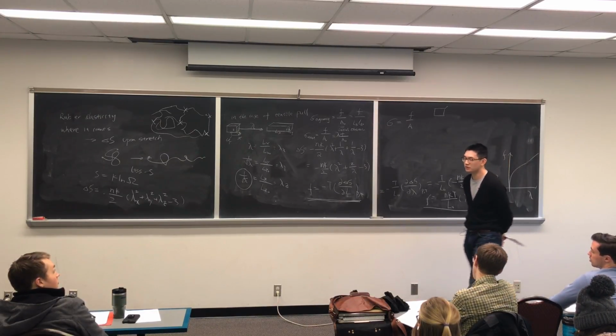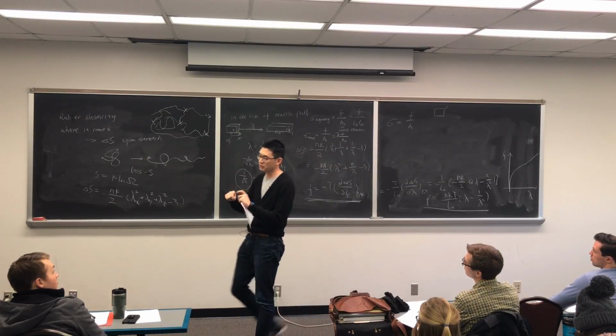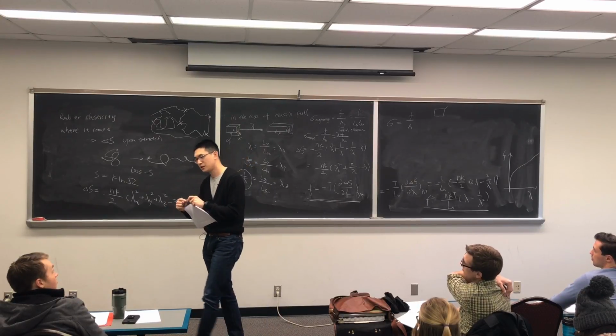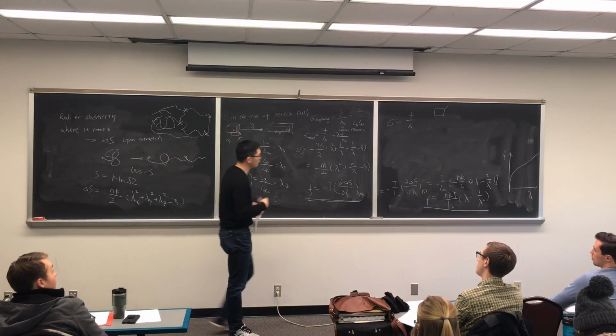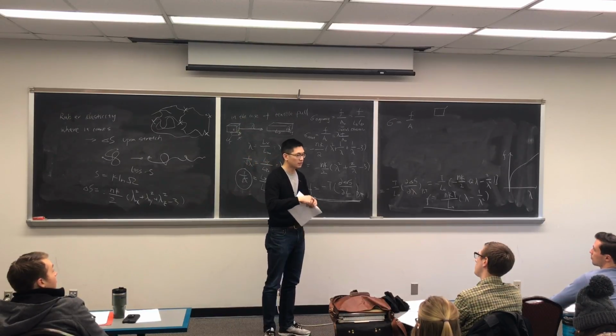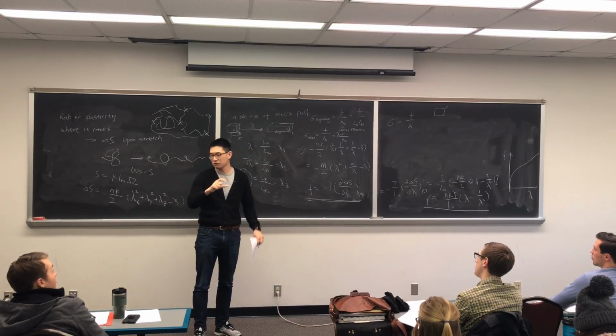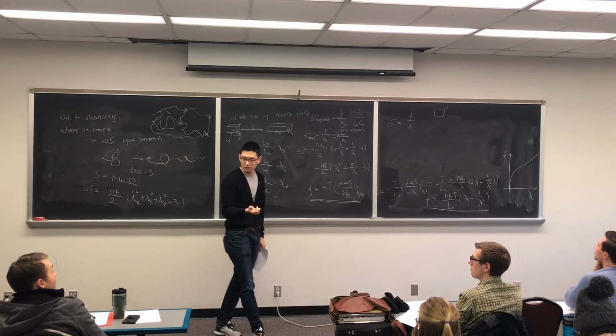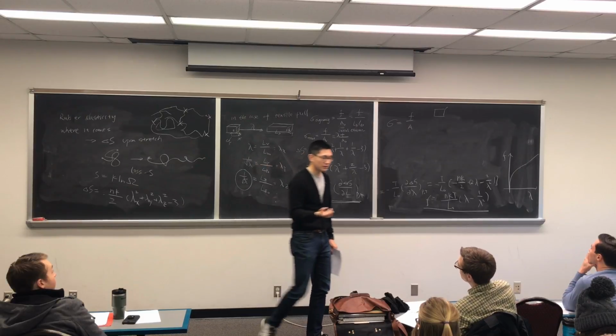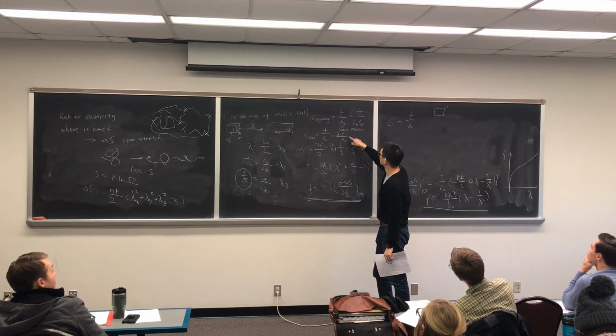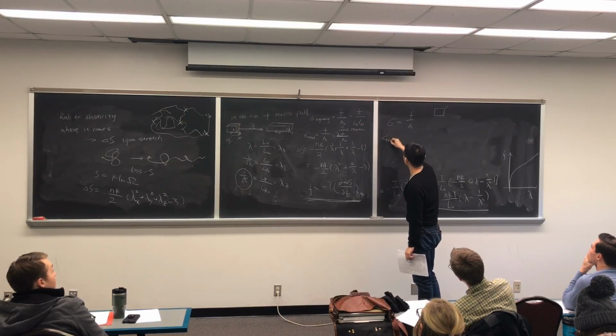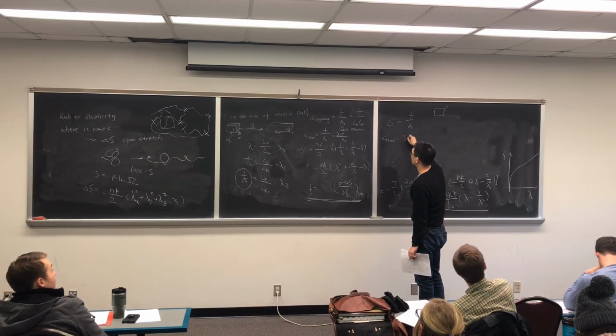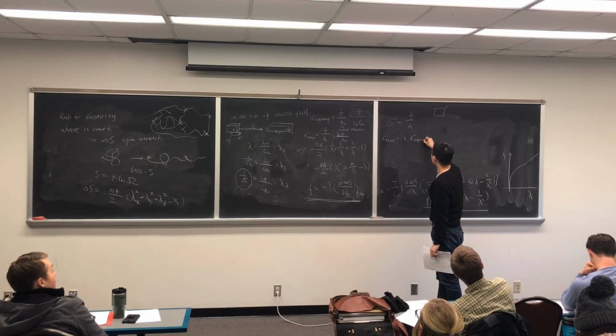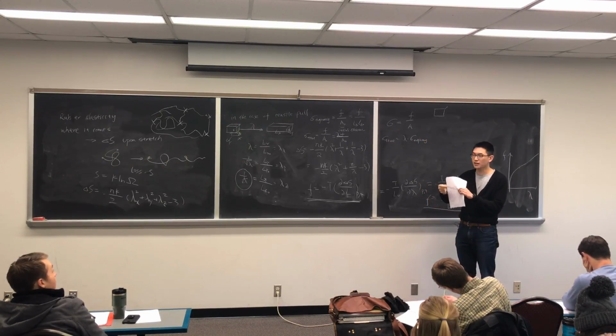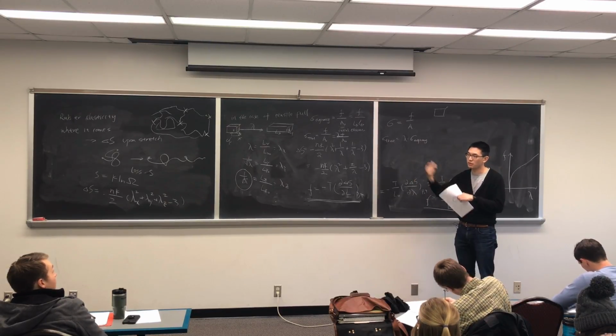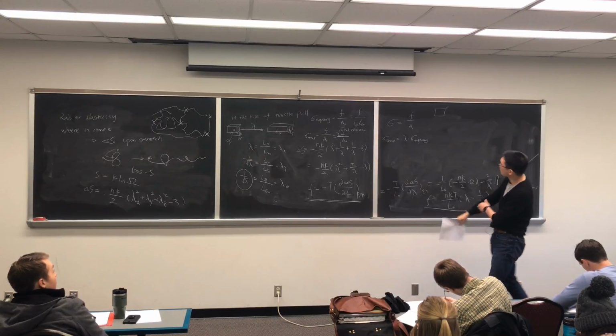Easier to measure. Easier to do, because as Chris mentioned, you don't always have a good way to measure how much cross-section area a sample has while it's being stretched. However, you can measure the length. If you assume it's an elastic, incompressible material, you draw in one direction, it's getting bigger. The other 2 directions are going to shrink at the same volume, right? So that's why this would always be a factor of lambda. So in other words, the true stress is always lambda times the engineering stress. If you draw it 2 times the length, your true stress happening in the film is twice of what you measure by engineering. Okay, some of the background knowledge for these 2.